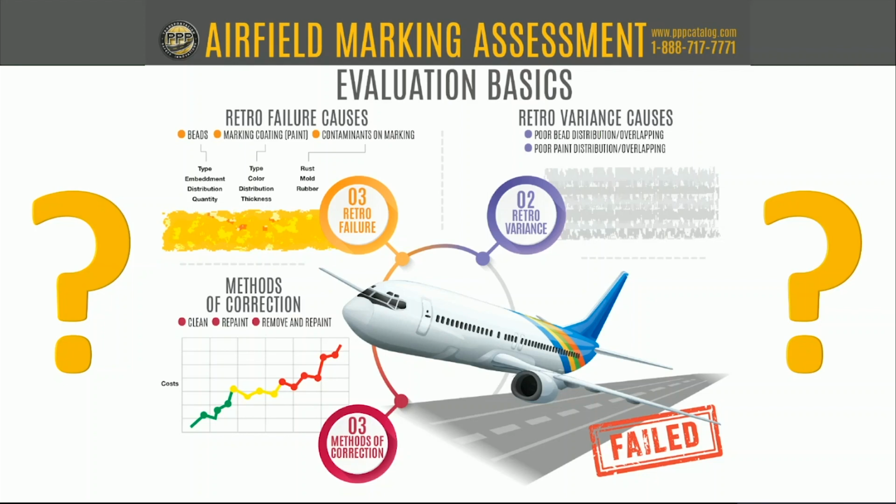We've got some data from Presque Isle, Maine, which is way up there in Maine. They were able to apply, I believe, a waterborne type 3 paint with type 3 glass. They were able to survive an entire winter and not have to paint the following year, which saved taxpayer money. I think it was like $250,000 to paint that. I might be wrong there, so don't quote me. But it was a significant savings just for one year, not having to repaint the entire airfield.